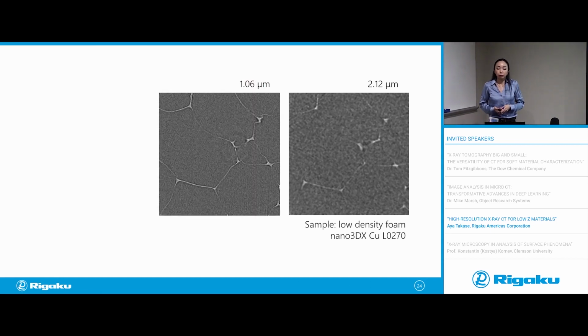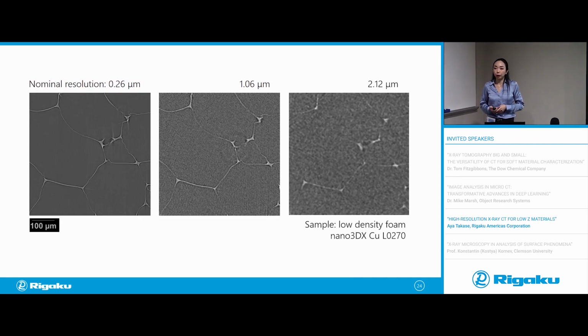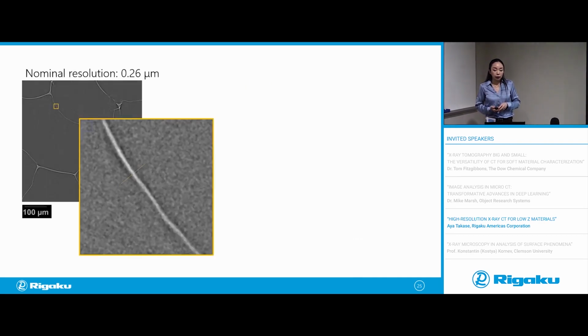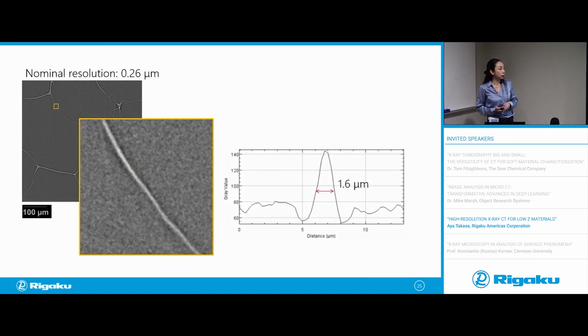If you use 1 micron resolution, it gets a lot better. If you use quarter micron, now you can see all the cell walls very well. And if you zoom into this high resolution scan, you see one of the walls very clearly. And if you look at a cross section of this, you can see that the wall thickness is about 1.6 microns. And this means that your voxel size needs to be probably 0.7, 0.5 microns at least to see this well.